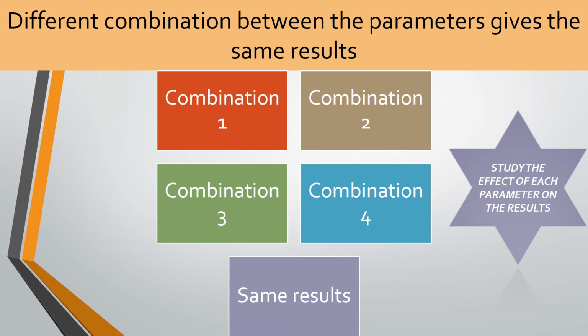So what we have found after using the direct method and the artificial neural network is that we have different combinations of 8 parameters, but the same results. How? Macroscopically, when we simulate the experiment, we find that our finite element results predict the experimental results very well. But if we look at the parameters, they are quite different, which means that how the voids behave microscopically is different.